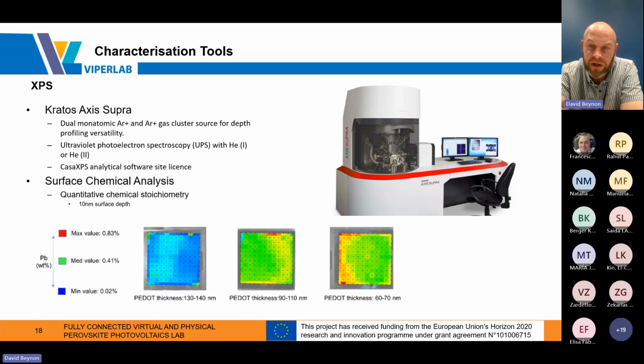In this case, we used a mapping function looking at the amount of lead that would be shown from perovskite as seen through the PEDOT layer coated on top. And what this allowed us to do is to identify where we might be getting a few defects across a larger area of the coating at lower thickness. We got a more uniform coating at a slightly higher thickness, and this is a higher thickness than would be optimal for spin-coated devices. And then once we got to even thicker, the device performance dropped off. We were getting a very good full coating, so we can't see the lead through in this device, but it wasn't optimum for the device performance.